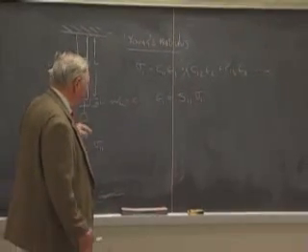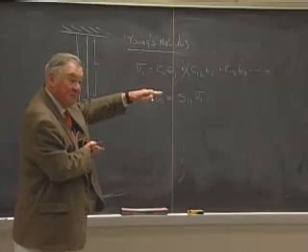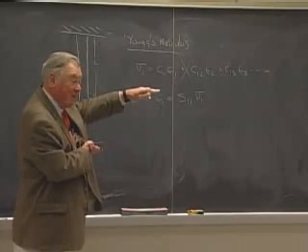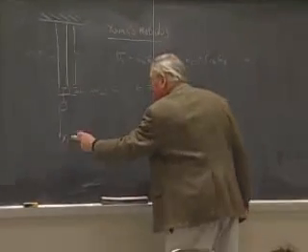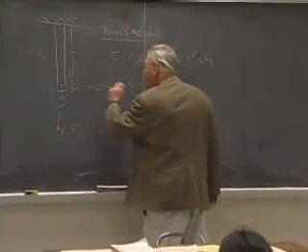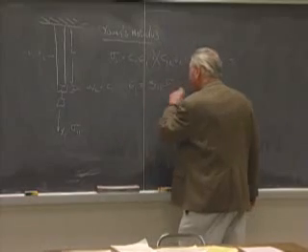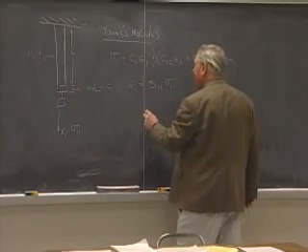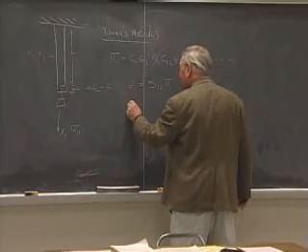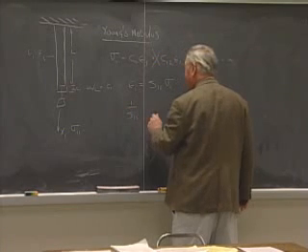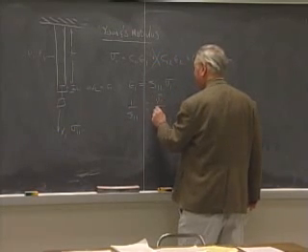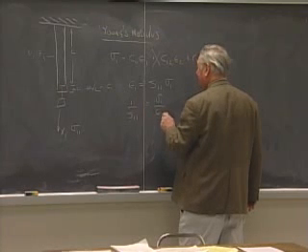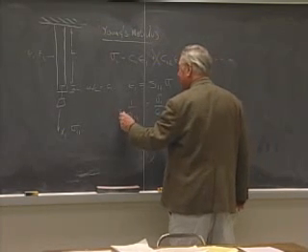You pull the sample in this direction, and what it does is shear. Well, if this were a single crystal, that would happen, and these would be other components of deformation. But if we apply sigma 1 and measure epsilon 1, then this is the way we have to define it. The definition of Young's modulus is that 1 over S11 is sigma 1 over epsilon 1, and this is Young's modulus.